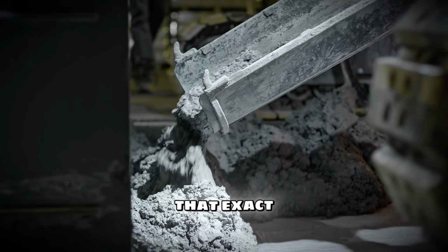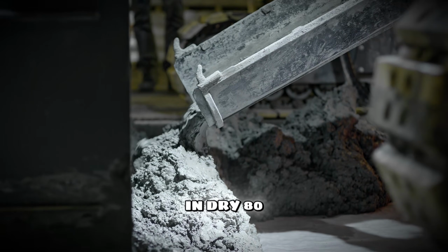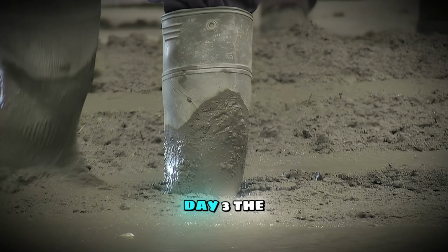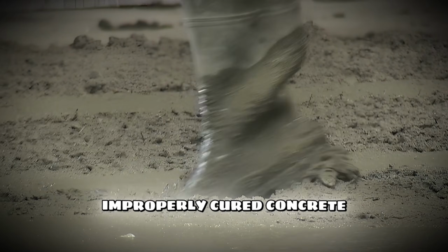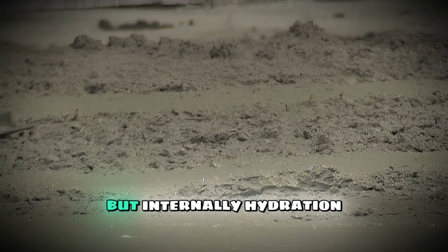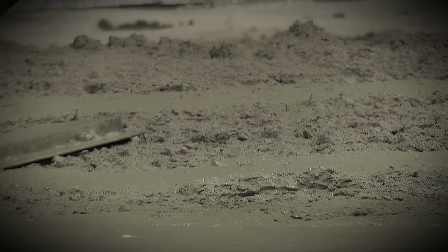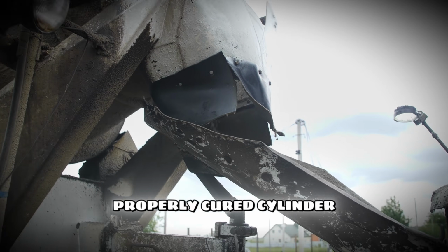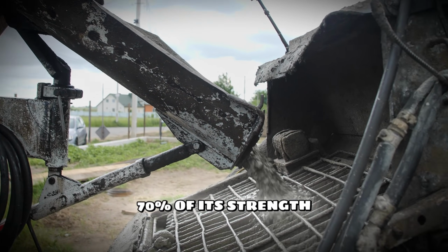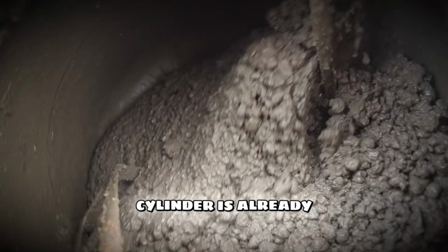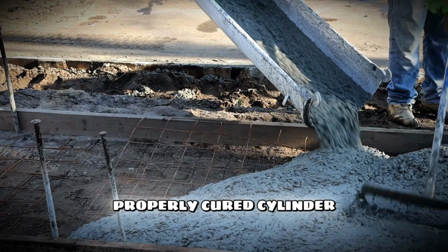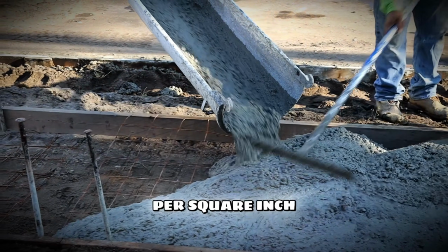Now let's take that exact same mix and leave it outside in dry, 80-degree air. Day 3. The improperly cured concrete might look fine, but internally hydration has stalled. Day 7. The properly cured cylinder is at about 70% of its strength. The air-dried cylinder is already lagging by 20%. Day 28. The properly cured cylinder hits 4,000 pounds per square inch.